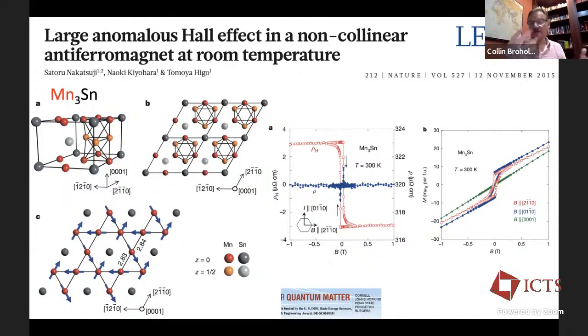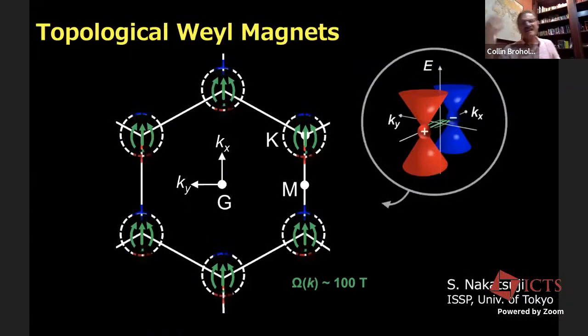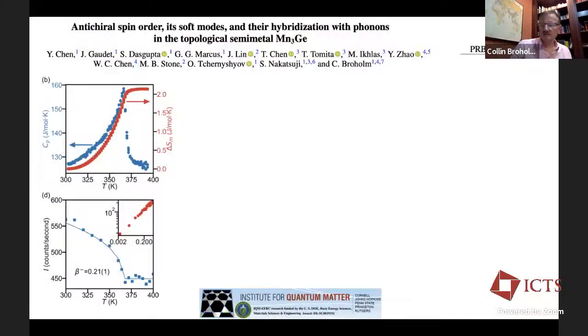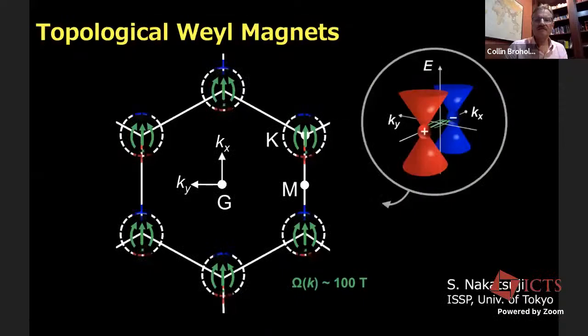On the other hand, the structure of the Kagome lattice is very important as well, because it leads to topologically protected Dirac points in the paramagnetic state, which then end up splitting apart into Weyl points that lie fairly close to the chemical potential. So that's the underlying explanation for this anomalous Hall effect: under the development of the magnetic order, these Dirac band crossings split apart, and we get Weyl points that carry Berry curvature, which in turn gives rise to anomalous Hall response and also anomalous Nernst effects.